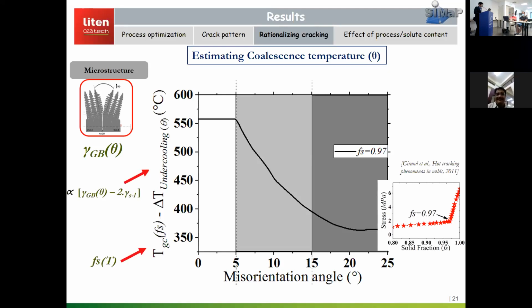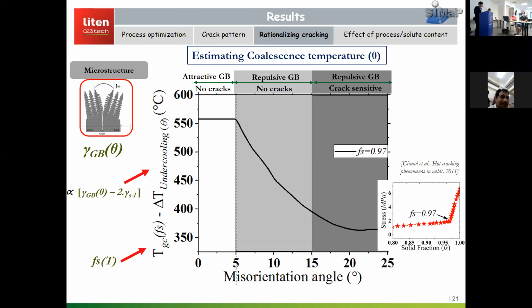Based on 0 to 5 degrees, the attractive grain boundaries, we know that those are non-cracking in nature. Once the repulsive grain boundaries come into the picture after 5 degrees of misorientation, the coalescence undercooling starts to develop, and the temperature decreases until a point. For example, at 15 degrees, we know that our repulsive grain boundaries will be crack sensitive. So at 15 degrees of misorientation, the critical coalescence temperature can be estimated. We estimated it at around 395 degrees Celsius for our alloy at 15 degrees and a coalescence solid fraction of 0.97.